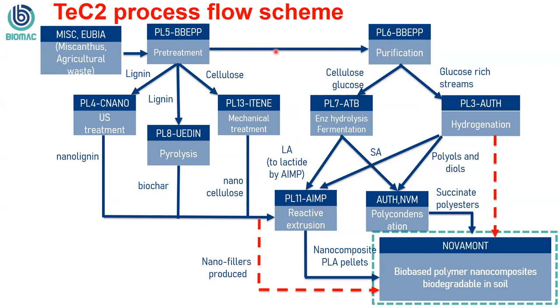All of these come together in a reactive extrusion process with monomers that are generated over here. So again, you can also see the feedstocks can be further treated, purified, converted, etc., to give us small molecules that can be used to produce polyesters. So we have our lactic acid, succinic acid, polyols and diols, and these are all being used either in a reactive extrusion process, for instance, using ring opening polymerization of lactic acid, or a polycondensation process, for instance, using succinic acid and various polyols and diols to make different kinds of polyesters. And all of these different biopolymers, coupled with all of these different bio-based additives, can be combined in a variety of formulations to give us some very nice materials for bio-based polymer nanocomposites relevant to agricultural applications and biodegradable in soil. So again, another example of how this can all work.